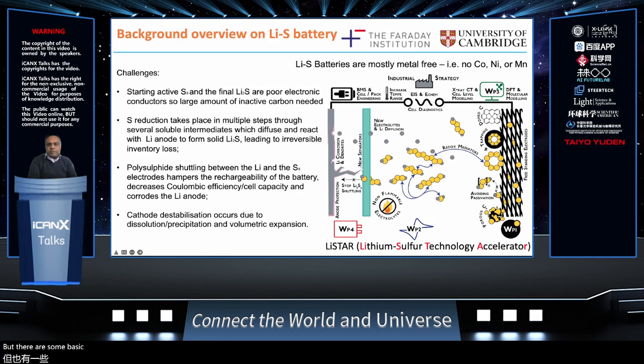But there are some basic problems that must be overcome for the lithium sulfur battery. First is that the sulfur is not conducting, pure sulfur powder is not conducting. So typically what's done is that you have a conducting scaffold on which the sulfur is loaded. And the conducting scaffold is typically porous carbon. Of course, if you use pure lithium as the anode, there are lots of issues related to formation of dendrites, but also the reaction between the lithium and sulfur forms polysulfide. And there's this effect of polysulfide shuttling, which can also lead to capacity fading of the battery.